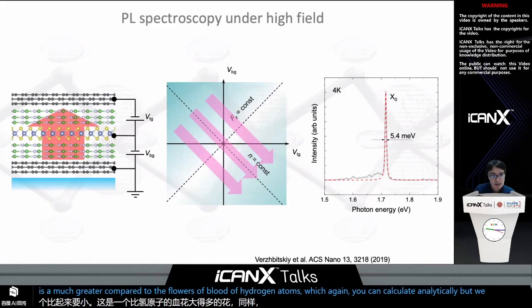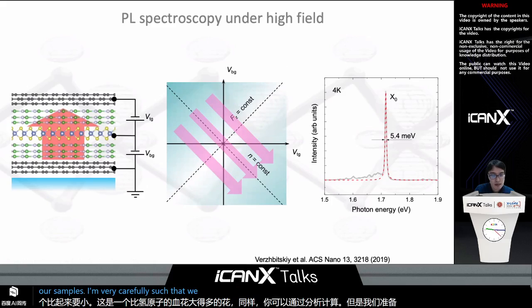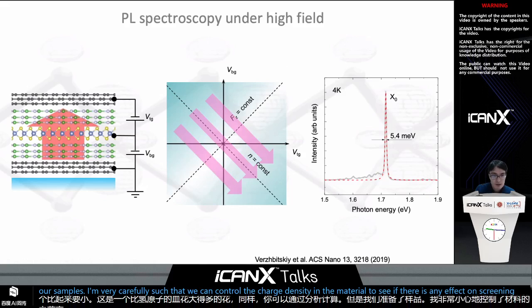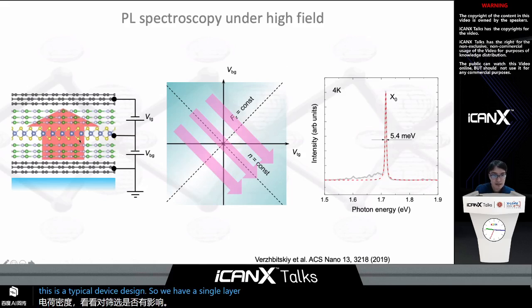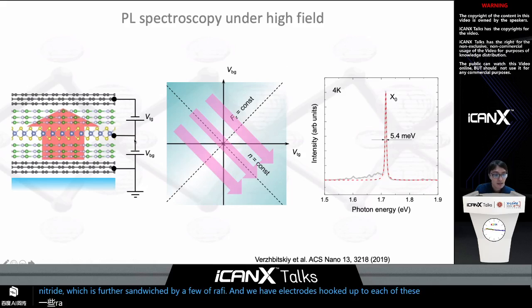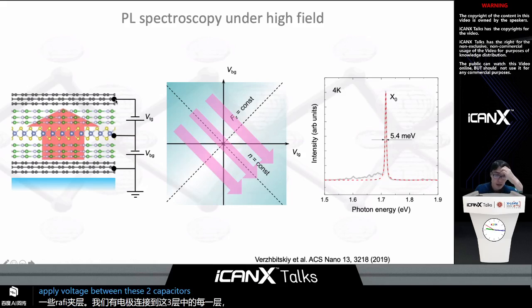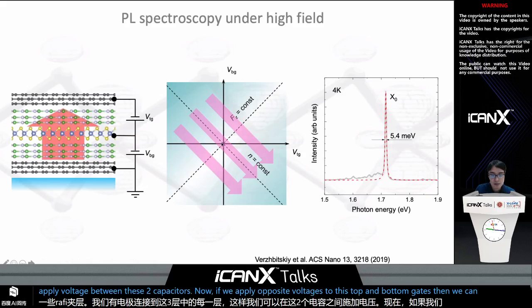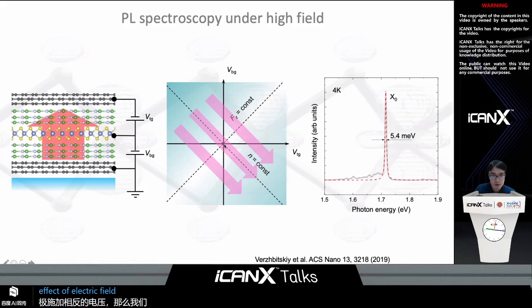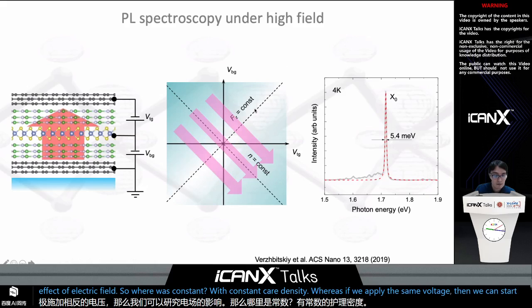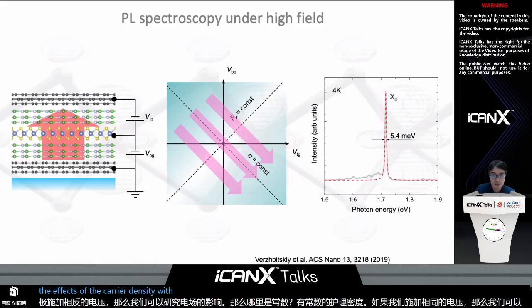But we prepared our samples very carefully, such that we can control the charge density in the 2D material to see if there's any effect on screening. So this is a typical device design. We have a single layer tungsten diselenide, which is sandwiched by an insulating hexagonal boron nitride, which is further sandwiched by a few layer graphene. And we have electrodes hooked up to each of these 3 layers, such that we can apply voltage between these 2 capacitors. Now, if we apply opposite voltages to the top and bottom gates, then we can study the effect of electric field with constant carrier density, whereas if we apply the same voltage, then we can study the effect of the carrier density at constant electric field.